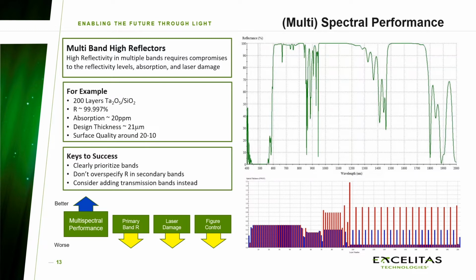You can see one example of a design that would be used to deal with this down in the bottom right. Much more complex than the previous one. This one has about 200 layers if we use the same materials. The reflection can still be pretty high, but we do have to choose between the bands and make sure that we're focused on the right band that matters for laser damage. This is a pretty costly coating, and when we do a coating this thick, this one's actually a 21 micron design thickness,